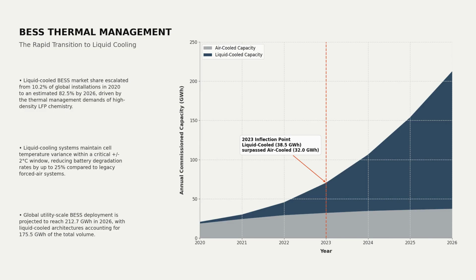The rapid transition to lithium-iron-phosphate chemistry has fundamentally altered the physical requirements of grid-scale energy storage. Legacy forced air cooling is no longer technically viable for high-density installations. Liquid-cooled architectures have escalated from 10.2% of global installations in 2020 to an estimated 82.5% by 2026.